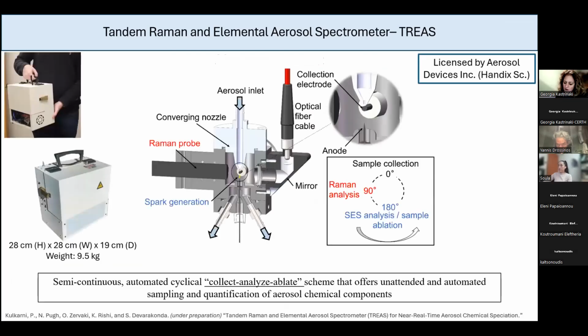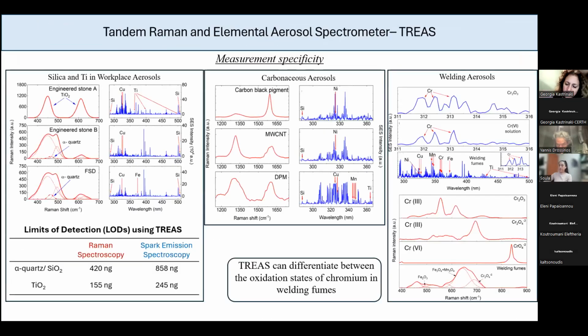Okay, so didn't you have any fluorescence? Usually you have an offset when you have fluorescence in your samples, or did you not detect any fluorescence in your measurements? I did detect fluorescence, but all the results that are shown here are corrected for the baseline. So basically, I was bringing everything down by correcting for the baseline. Okay, so by this correction you can adjust all those measurements for the comparison that you showed in your sample, where you said that the intensity of your measurement may be in correlation with the concentration of your sample, correct?